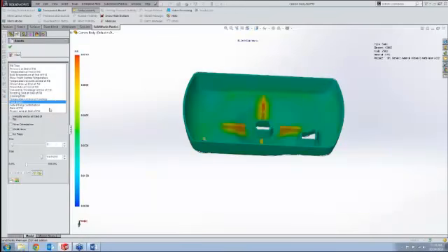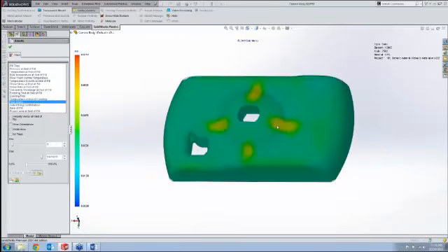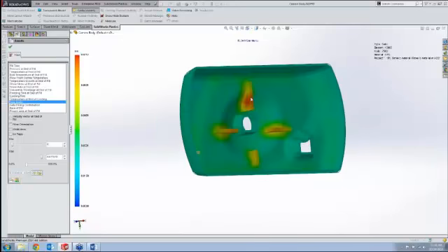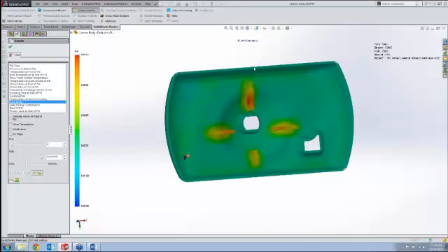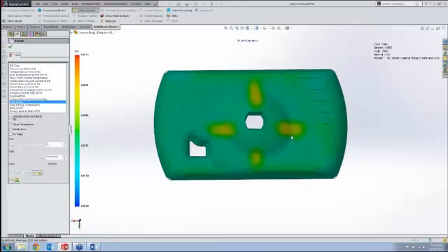There's a sink mark analysis on this as well, and what I'd like to point out here in particular is I've made these ribs very thick with regard to the plastic material here, and anybody that's got experience in the injection mold plastics industry knows that's probably not a good idea. I did so on purpose here to showcase the sink mark analysis. Now, in the professional and standard package, this isn't necessarily a depth, but more of a ratio of sink mark. In the premium level package, it will actually give you the depth of sink marks as well.